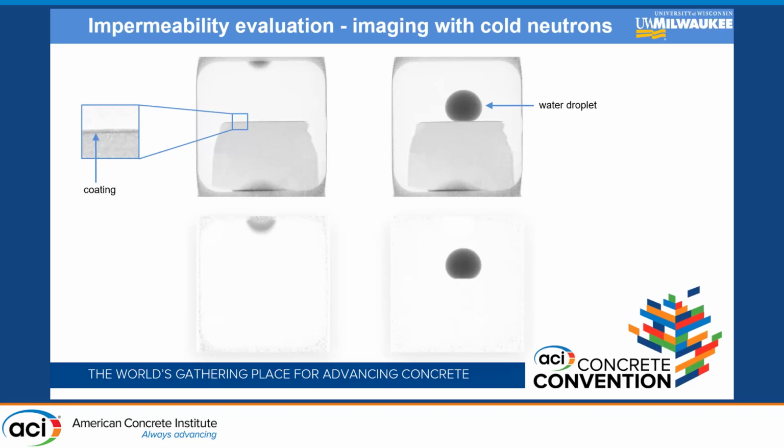We are bombarding the sample, which was the ceramic sample, 9 by 9 by 9 millimeters in dimension. And we were able to see what the coating thickness was. The layer is uniform, water droplet contact angles are hydrophobic to super hydrophobic, no water going in. How these pictures were created: we subtract the dry image from the beginning, without any droplet, from the dynamic images when the droplet was coming, when we were setting the droplet and waiting to see what would happen.